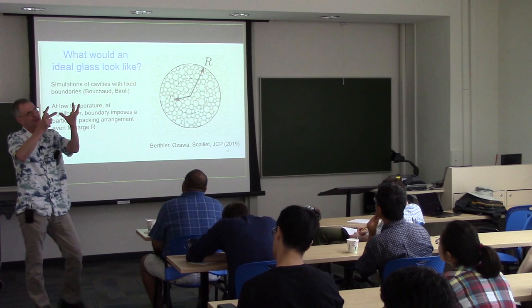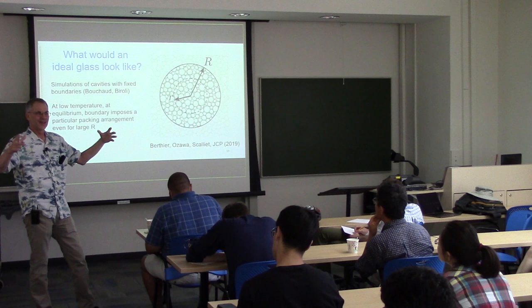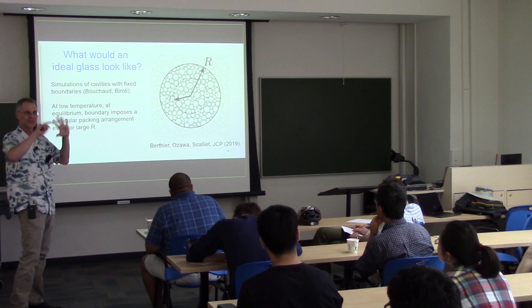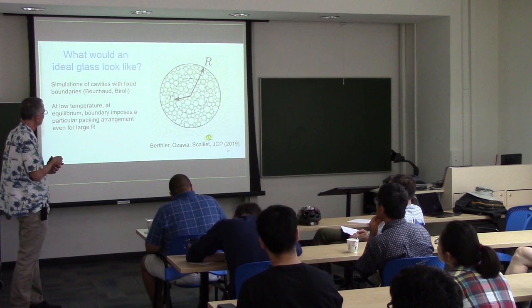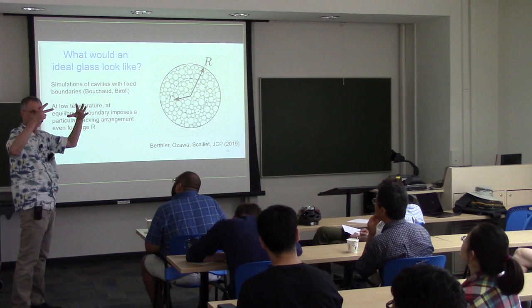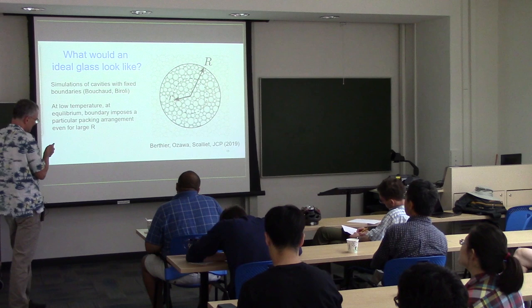And as you equilibrate your system at lower and lower temperatures, the size sphere you have to pick gets bigger and bigger. For the best simulations at the lowest temperature, I think it's 8 particle diameters across, so there's something like 150, 200 particles in this sphere. And you might think, how is this amorphous boundary condition possibly able to communicate all this information and recreate the packing of those particles? Well, that's the loss of configurational entropy. The system is running out of ways to be packed, and you can measure that in this simulation.